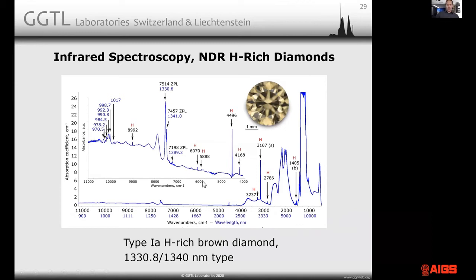Now, with our new capacities to go low temperature in this range, we recorded here an infrared spectrum that ranges all the way to 900 nanometers. And the entire range from 4,000 wave numbers to 11,000 wave numbers is low temperature spectroscopy. So this band at 7,500 actually splits at low temperature into a doublet at 7,514, 7,457, and a very strong vibronic component that ranges probably to about 1,000 nanometers.